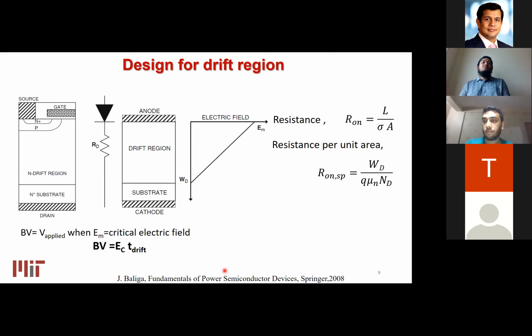So if you do some simple math, which is shown in this book here, what we end up with is basically the figure of merit of a power MOSFET for the drift region, this equation, which is called the Baliga figure of merit. This is a ratio of the specific on-resistance over the blocking voltage squared. And as we can see from the right-hand side of the equation, this is a function of only the material parameters: the dielectric constant, mobility, and the critical electric field. And our goal is basically to minimize this figure of merit on the left-hand side. So we need to minimize the resistance, minimize the switching loss, and increase the blocking voltage for a particular application.